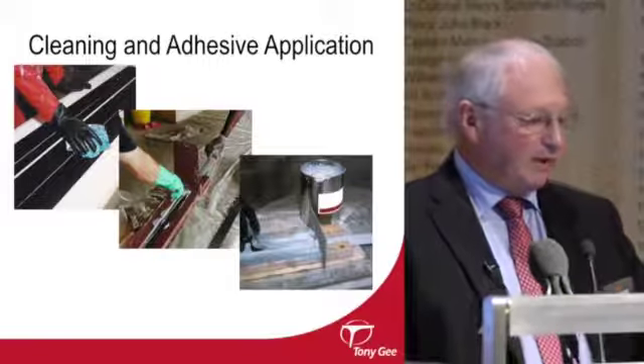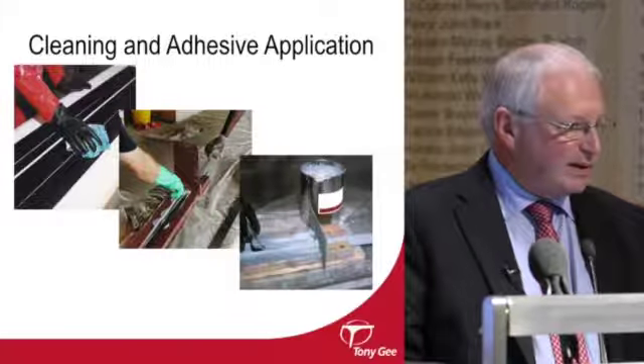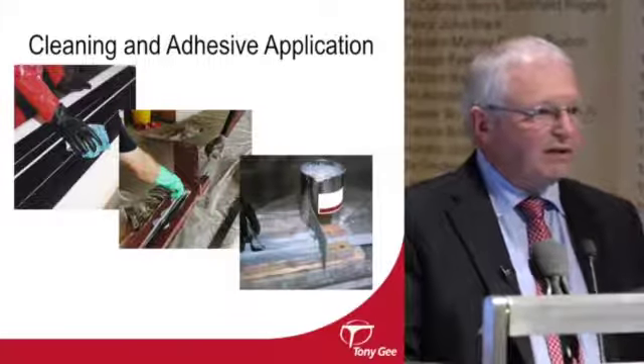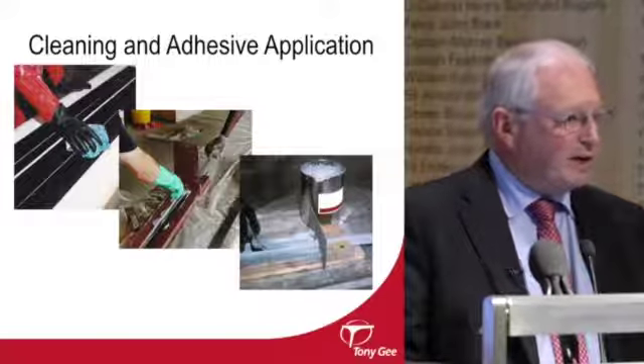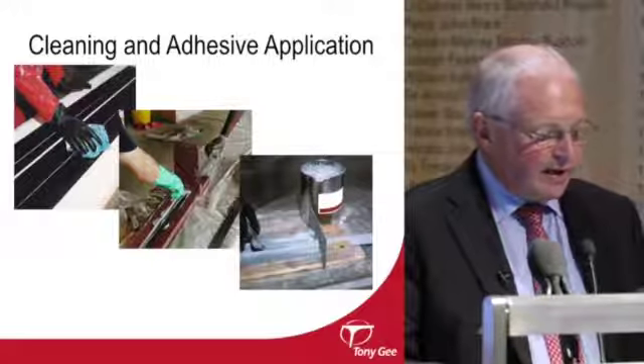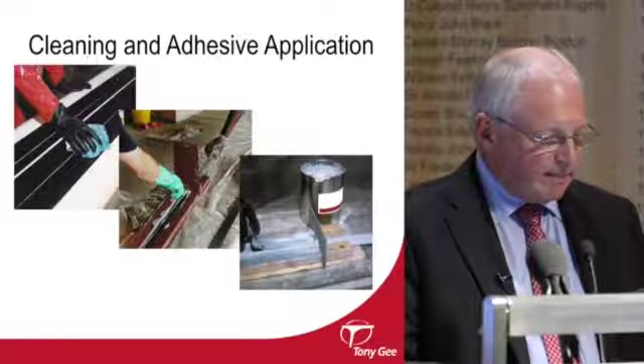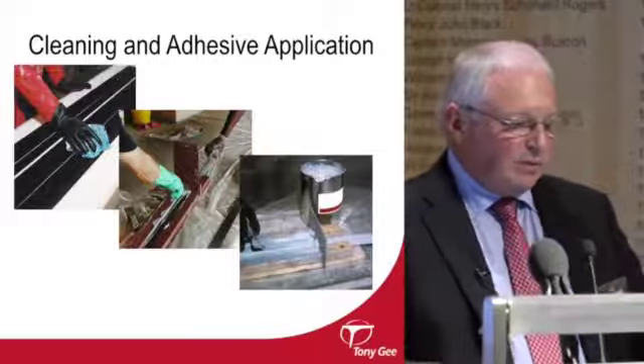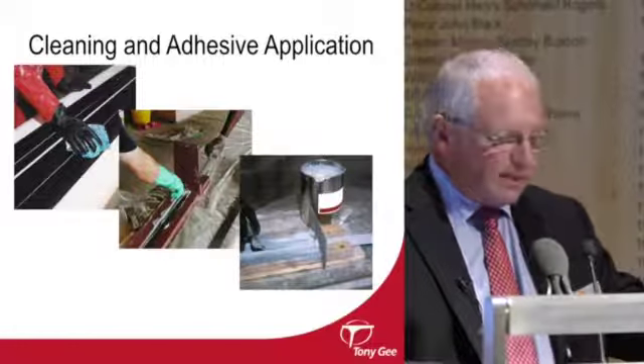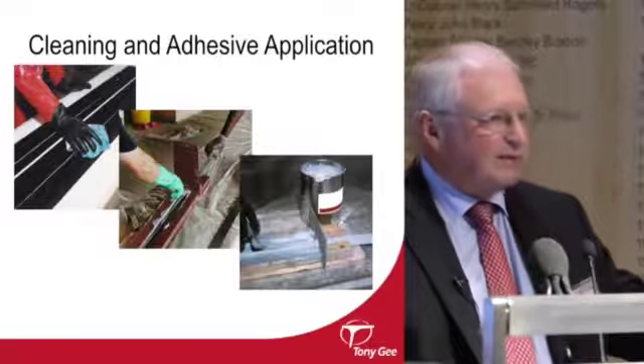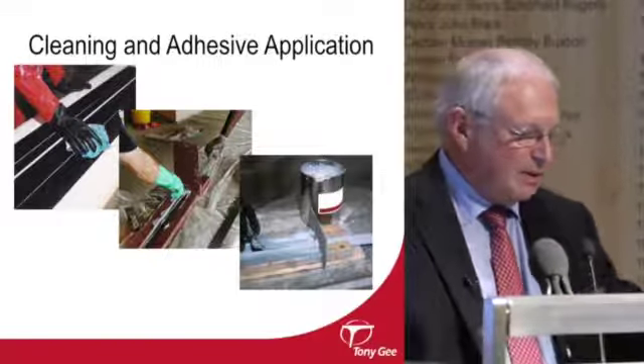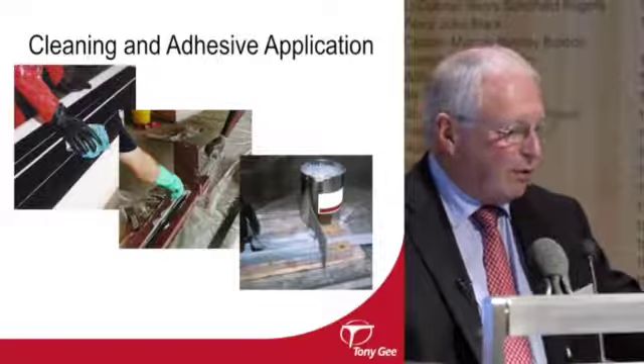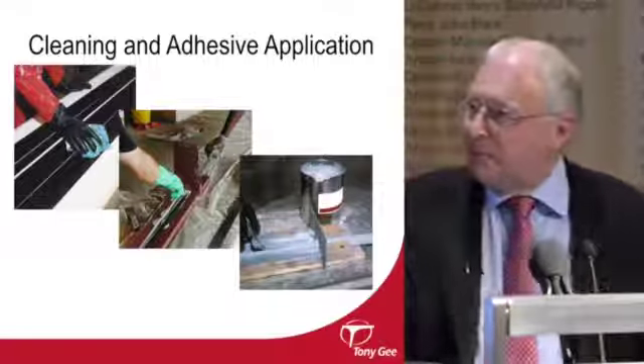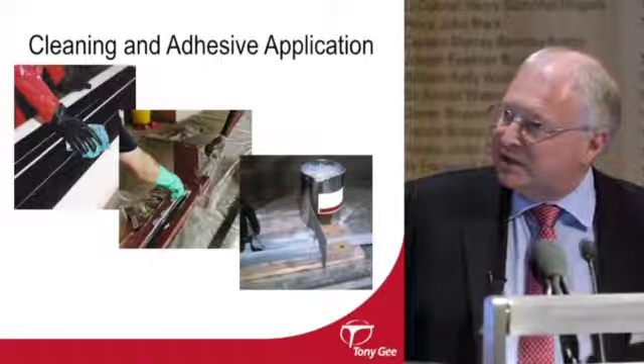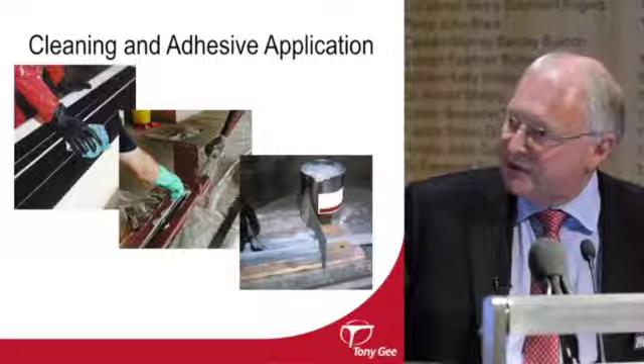This should be done not with white spirit, because that can leave a residue on the surface, but there are proprietary cleaners that the likes of Sika have available to undertake this. Then when we mix the two-part epoxy adhesive correctly, the adhesive is applied into a bath. It's usually between two timber formers, which is what's happening here, and you can see the strip is being pulled out of the end.